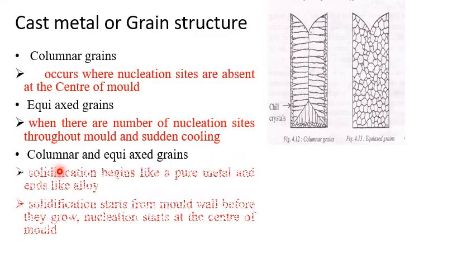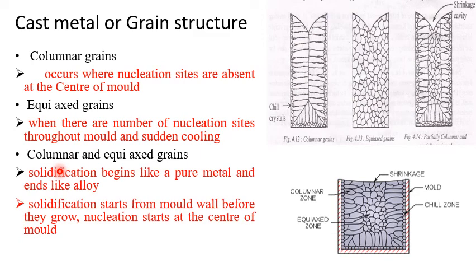Next is a mixture of columnar and equiaxed grains. Here the solidification begins like a pure metal and ends like an alloy. The nucleation sites are going to start at the middle of the mold cavity, and even at the mold wall. Whenever they start at the mold wall, they grow like columnar grains, and the nucleation sites which are present at the center will form the equiaxed grains.